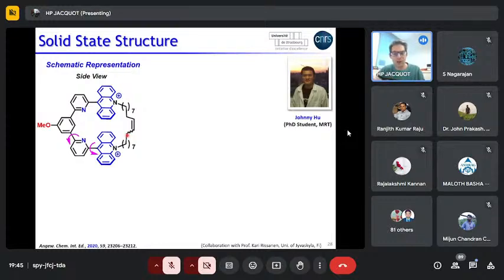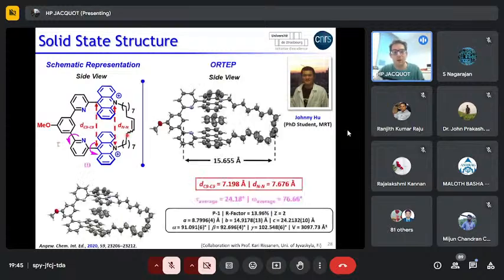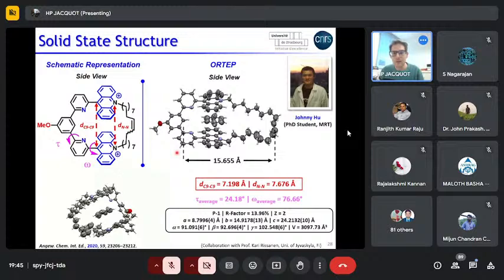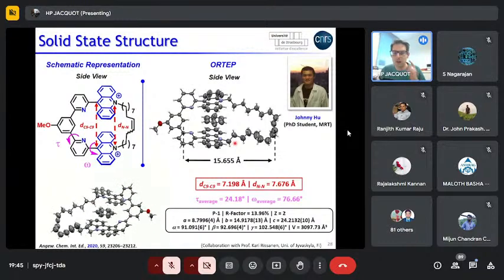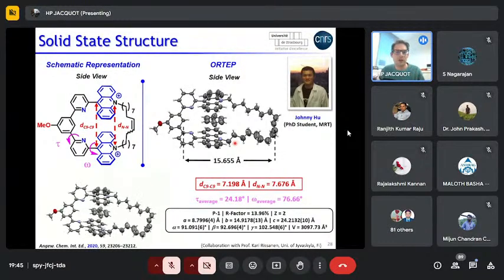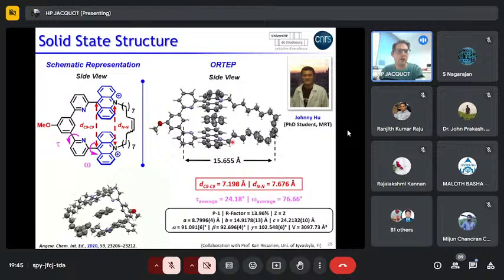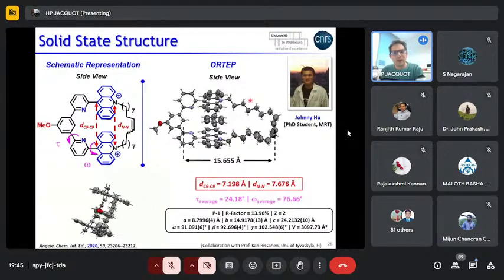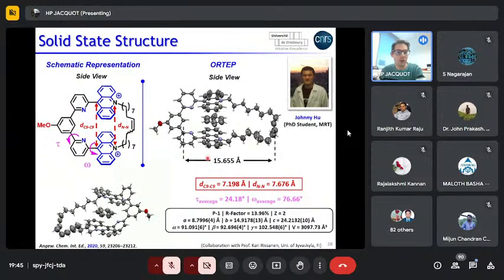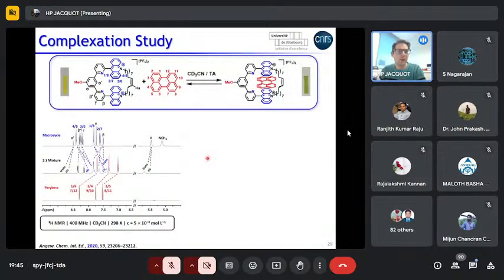And then he just had to filter the solution to get the pure compound. Also, Johnny was very talented and lucky because he was able to grow crystals. And we see that the molecule indeed crystallizes with one benzene molecule inside its cavity. So this benzene comes from the crystallization conditions since benzene was used as a non-solvent. So we can start thinking here that this receptor is good to do some host-guest chemistry, more especially in solution. So one example I show you is with perylene.